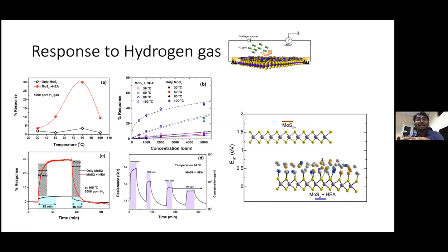And what we found was that the energy for these particles was much lower than that of the bare MoS2. That means it can readily adsorb this hydrogen, and that adsorbed hydrogen can give a large change in the current. Another reason was that you have a Schottky barrier, and even a smaller increase in the carrier concentration on one side can result in a larger current. So that amplifies your change in the current, and what we saw is something like a 10 times enhancement in the response to hydrogen, and that was communicated to Nanoscale.